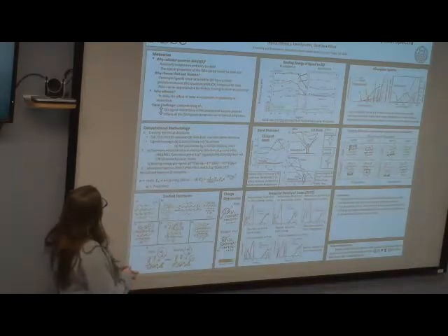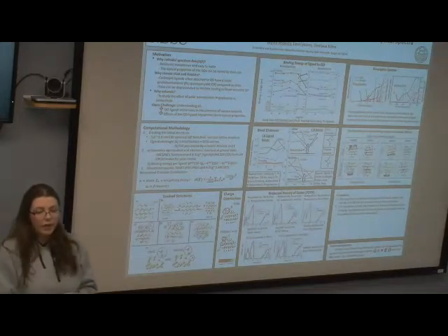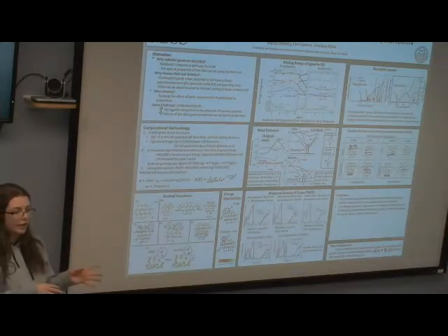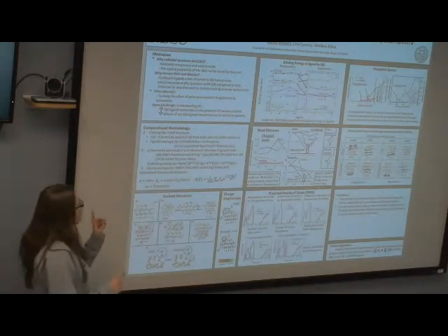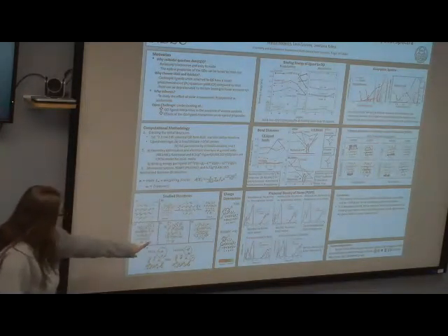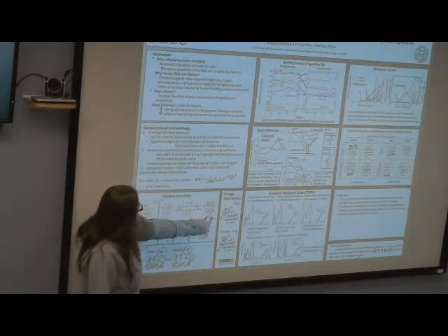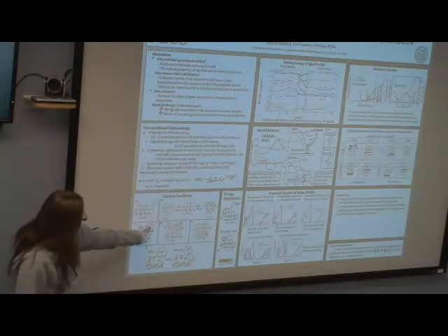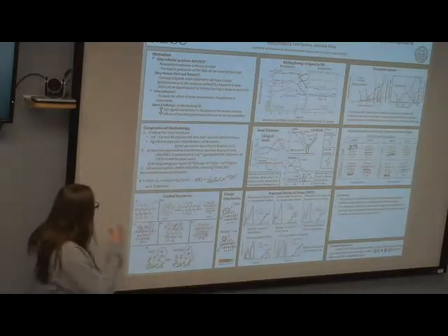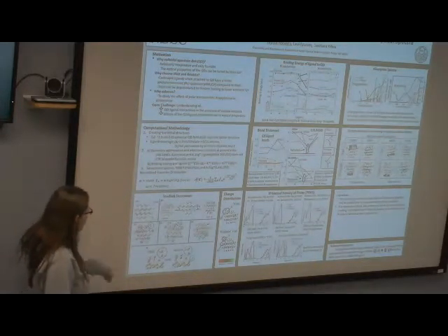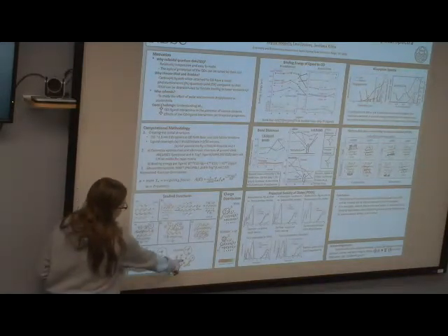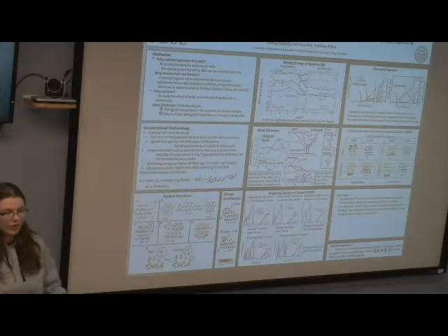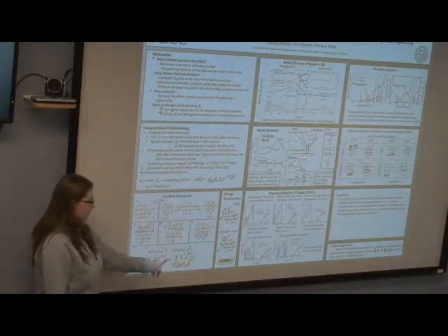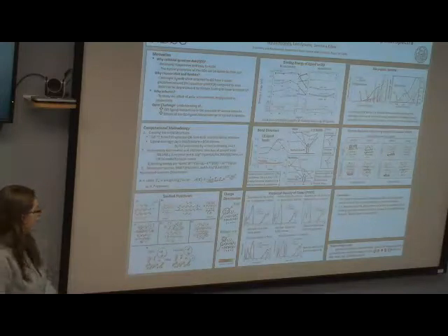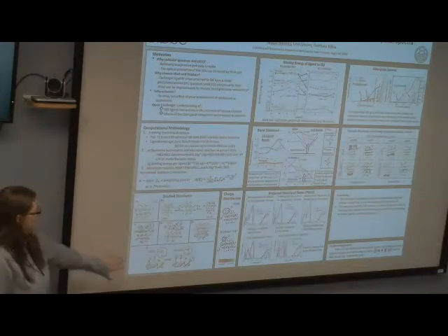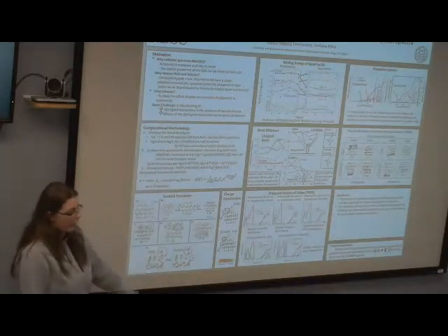And then it is passivated with either one thiolate and no amines, or one thiol or thiolate, or one ligand, and then either has 20 amines or has no amines. You can see that down here. This is the amines with the one thiol, or thiolate, on the surface. And then otherwise it can be passivated with solely one thiol or thiolate. This is not in real life, this doesn't happen, but this is just observed so that we can figure out the optical properties specifically that correlate to one thiol or thiolate.